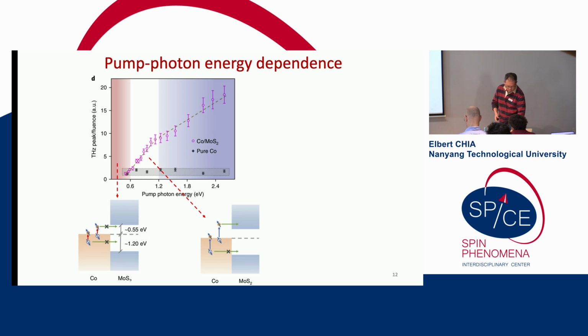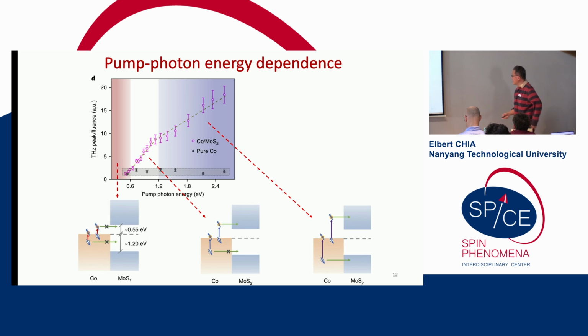So what happens when we pump higher than 1.2 eV? In this case, both the spin-up electrons and the spin-down holes have enough energy to overcome the electron and hole Schottky barrier, respectively. However, the contribution to the injected spin current from the holes is opposite to that from the electrons. And so the net effect is that you have a smaller slope here.